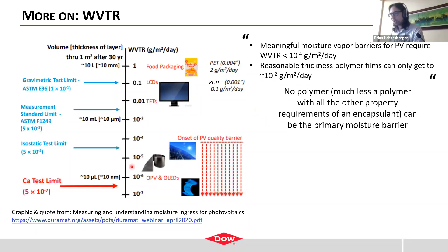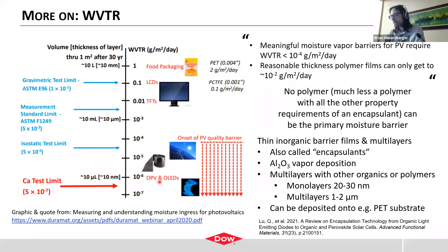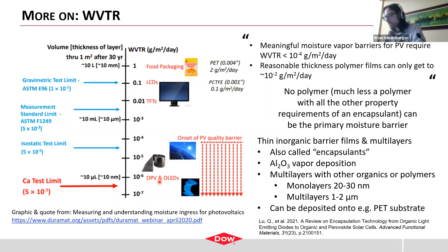Things like edge seals are polymer-based but are actually loaded with inorganic desiccants — combining a polymer with some other material or chemistry in order to provide additional moisture barrier. You might wonder how OLED devices exist with this level of sensitivity. There's another class of materials also called encapsulants, made from thin inorganic barrier films and multi-layers. These can be aluminum oxide vapor deposited in relatively thin layers, sometimes combined in multi-layer polymer–inorganic stacks deposited onto a PET substrate. This is a different class, and I've included a reference to a review of this type of encapsulation technology for very sensitive devices.